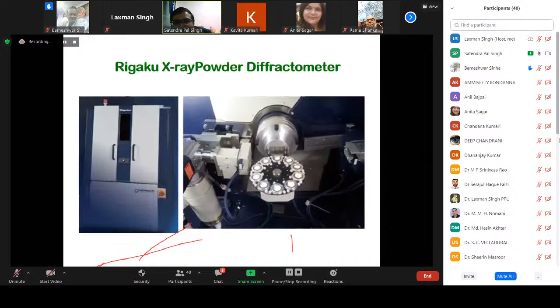One of the instruments is the Rigaku powder X-ray diffractometer, which looks like this. Maybe people who are not familiar can see. This is in our lab. Here we are using multiple samples, but generally the sample holder consists of only one. But since we are using combinatorial chemistry, we need so many X-ray patterns at a time, so we can use a multiple sample setup, and this sample holder gets rotated when the X-ray beam falls and gets detected. So the instrument looks like this.